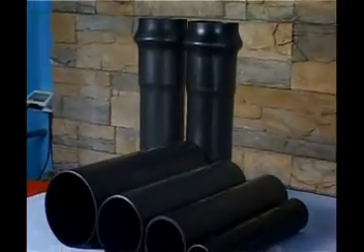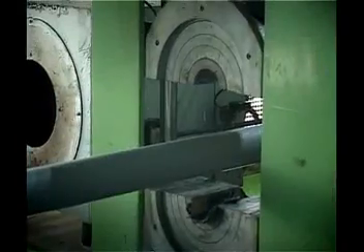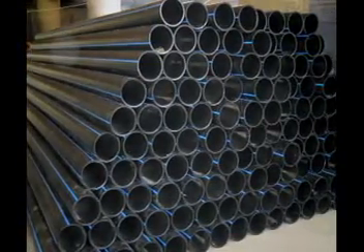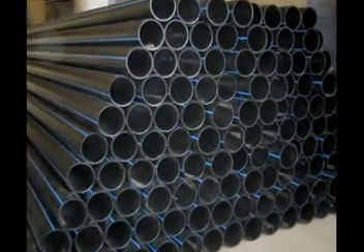The carbon black UV stabilized KiTEC PVC pipes, when subjected to in-house UV exposure using UV B340 lamps to short-term wavelengths in the region of 365 nm to 295 nm for 300 hours, performed far better in comparison to other UPVC SWR pipes. KiTEC has also established facility to manufacture polyethylene pipes up to 200 mm OD, and the same are supplied only on customer needs.